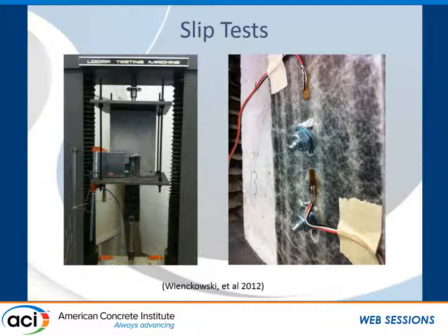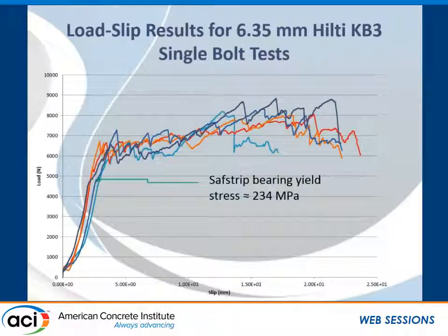Now, the free end slip of the connection versus the applied load was what we were mainly after, and you see some of the results of the slip tests here in the load slip curves that I'm showing you.